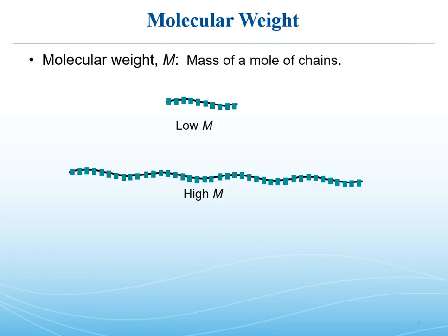So this is totally analogous to, say, methanol having a lower molecular weight than ethanol. The big difference in the case of polymers is you can have maybe a 5% change in molecular weight, and while you will change the mechanical properties and diffusivity and viscoelastic properties, it will still effectively be the same material. Polyethylene with one molecular weight is still polyethylene if you switch the molecular weight.